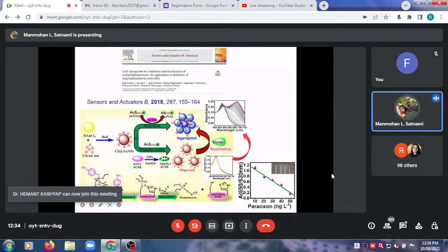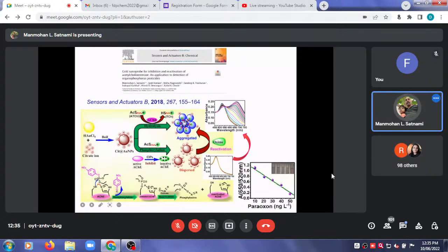In the presence of acetylcholine esterase, the acetylthiocholine is hydrolyzed to form acetic acid and a thiol containing group. The sulfur of the thiol containing group shows very good affinity with gold nanoparticle because of the soft acid base principle. So when this sulfur binds with the surface of gold nanoparticle, it induces aggregation. As the gold nanoparticle is aggregated, its size increases, and the color changes from reddish to blue, and it will give absorption at 655 nanometer. You can see from here, the absorption at 520 nanometer is for gold nanoparticle. As the size of gold nanoparticle increases, the absorbance at 655 nanometer increases, and at 520 nanometer decreases.